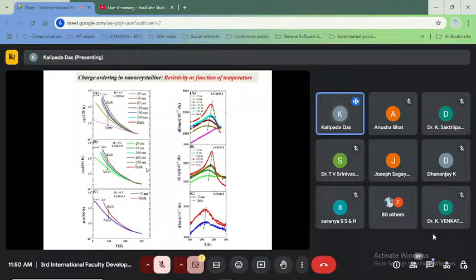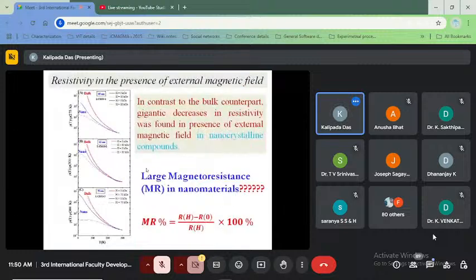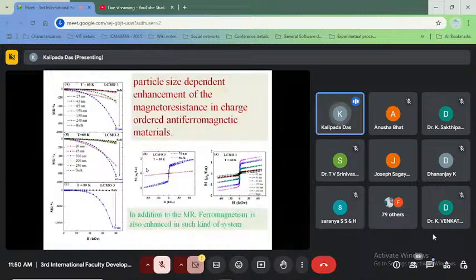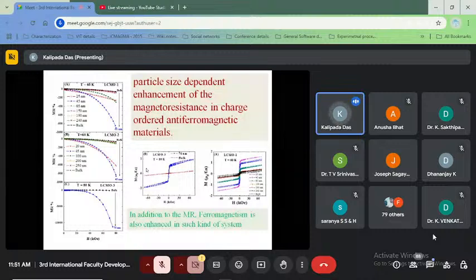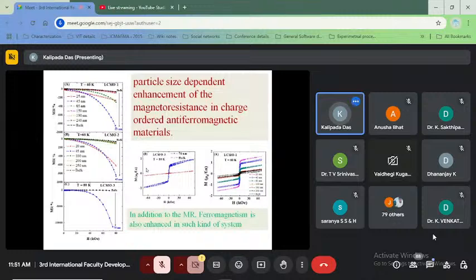Hence, from this, we can easily guess that the ferromagnetic part may be enhanced, because already in the magnetocaloric effect we have seen that the ferromagnetic part is enhanced. We have now calculated the magnetoresistance, and a systematic change of the magnetoresistance from bulk to nanomaterials appears. In the nanomaterial, the magnetoresistance is enhanced in all cases. Similarly, just for comparison, we have plotted the magnetization versus field, and we see that with respect to particle size, the magnetization also gets enhanced.